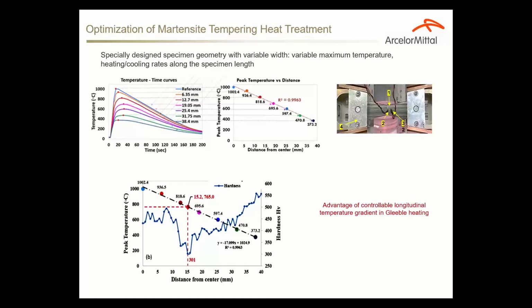This is an example of how we use that flexibility to study tempering of martensite. So we loaded a sample with variable widths into the Gleeble. We measured temperatures and then hardness at those locations simultaneously. So you can see how the martensite was tempering, and what kind of microstructure, just using a couple of samples, not many samples. Machining costs money, costs time. Testing costs money, costs time. This allows us to save a lot of time, money, and labor in performing our tests.